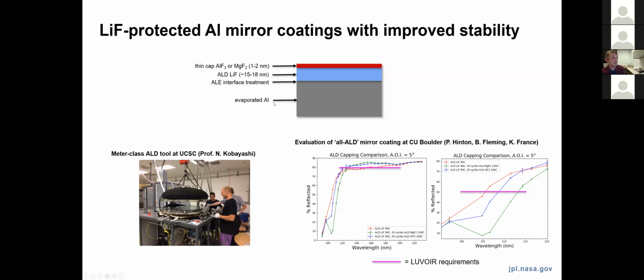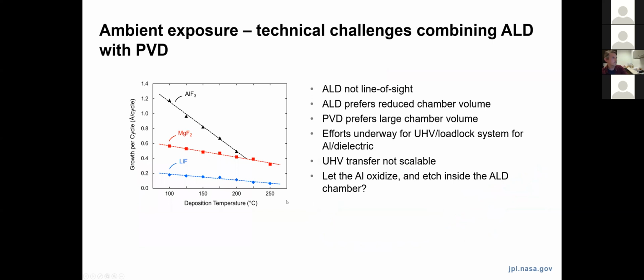In the meantime, we've also been creating some of these protective coatings, again, all deposited with atomic layer deposition, investigating different choices of cap material, as I'm showing in the lower right here. But even these all-ALD films have advanced to the point now where we can create a coating that meets the LUVOIR requirements, although again, still at relatively small scales. I'm going to skip a little bit through some of this.